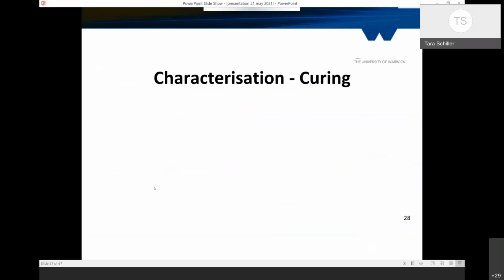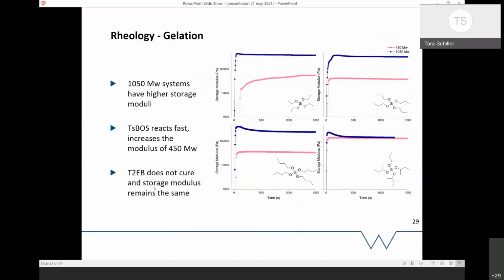So Andrew's done a really neat job of looking at characterizing the curing. What we did was look at the rheology and IR curing with it. What we noticed with some of the materials, they were curing way too quickly to allow kinetics to be run with it too. So we had to work out what we could run to look at things. So you can see here we've got the different monomers with it. Some of the materials reacted too fast, some of them just didn't cure. They just basically get a little bit more viscous, but not go through completely with it.